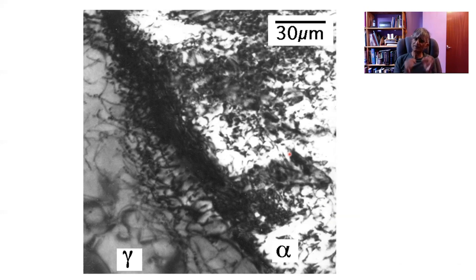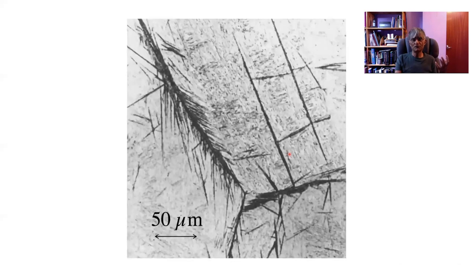So this means that bainite plates, even if they don't collide with an austenite grain boundary, will stop before they're fully evolved, before they reach a formidable barrier like an austenite grain boundary. So if we look at the optical microstructure illustrated here, the dark regions, as I said to you, are clusters of bainite plates. And they etch darker because they are clusters of bainite plates with intervening phases. So there are lots of interfaces for the etching to attack, whereas the martensite in the background is untempered and therefore has very little structure.